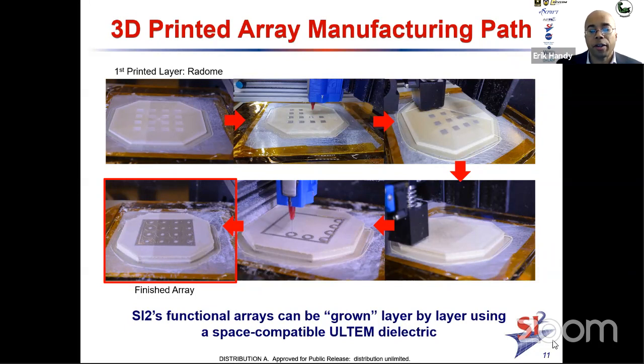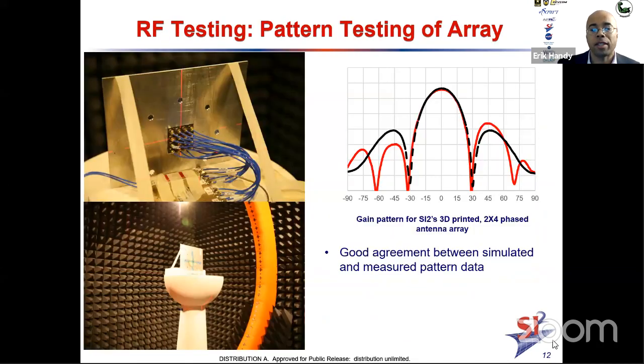Now that structure is ready for drilling vias down to the buried patches and attaching COTS connectors. So we show we can grow up this whole structure like the Vivaldi without touching the part, just going back and forth between dissimilar materials. We take the array into the chamber and we see performance that aligns very nicely with simulations.